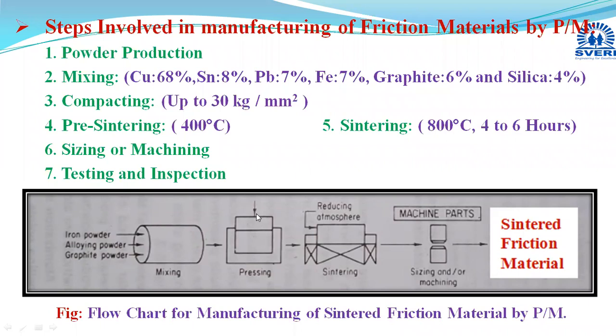that component is ejected in the third step, which is termed ejection, and the component obtained is termed green compact. You have to select the proper pressures. Here you have to mention the pressure value. Then it is subjected to pre-sintering, which is done at 400 degrees Celsius.